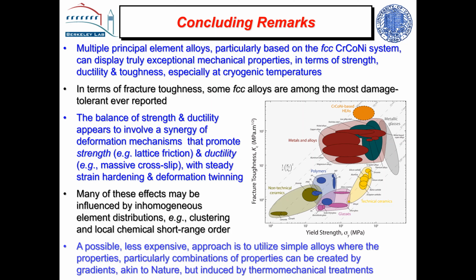So you predict that in almost any high entropy alloy, you would expect an increase in stacking fault energy with short-range order, because we are studying BCC medium entropy alloys, and we are not sure yet, but from calculations, we might see a decrease in stacking fault energy, very small, but that's why I'm asking.